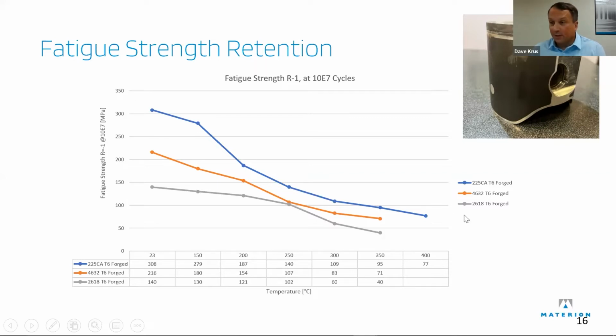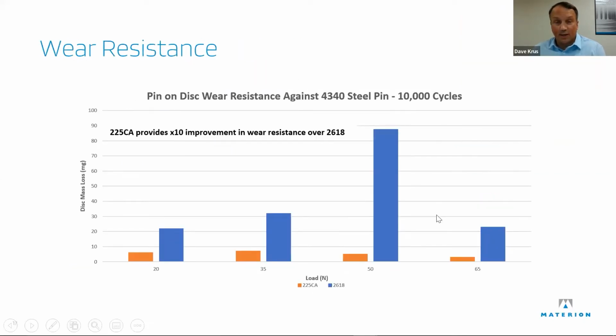Looking at wear resistance. So this is a pin on disc sliding back and forth. There's a 4340 steel pin on either, in the brown, a 225CA disc, or blue is a 2618 disc. And you can see there's an appreciable factor of 4, even higher, when it gets really high, the mass loss is a lot in the 2618. And actually, the reason it comes down here as we go to a higher pressure is because you're actually deforming the material and not scraping it off. So it's not losing mass. It's just moving out of the way.